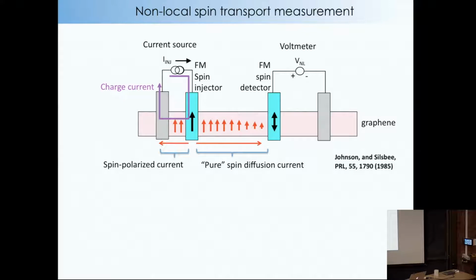So these red are the conduction electrons inside the graphene. And what happens is that the charge current flows to the left through this loop. But spins have a mind of their own. Some of them get pushed to the left, but other ones just decide to diffuse. They diffuse in all directions, actually. And some of them decide to just diffuse to the right. And when they reach the second ferromagnetic electrode, this is a ferromagnetic spin detector. And what you do is you measure the voltage between that and a non-magnetic electrode. And the voltage will tell you the spin polarization underneath this electrode. Okay, and this is called a pure spin diffusion current or a pure spin current.